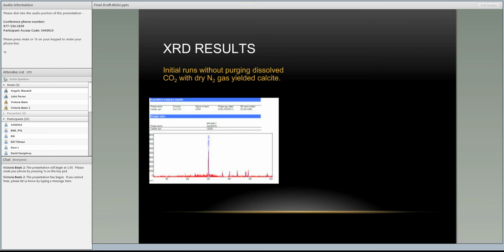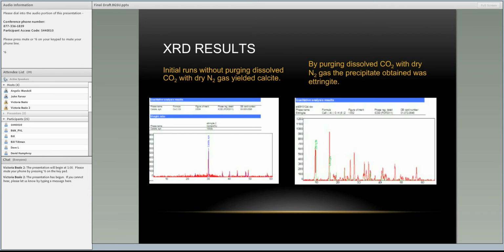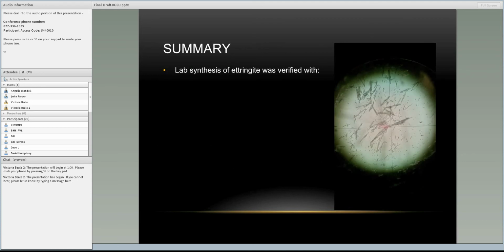With the lab ettringite we created, we were also able to look at it with a petrographic microscope, so that's what you're seeing there. The needles were pretty large. So we were able to create the lab ettringite. We were able to see it with a microscope and also with SEM images. We were able to get an EDAX composition to compare to, and also to get a standard with the XRD.